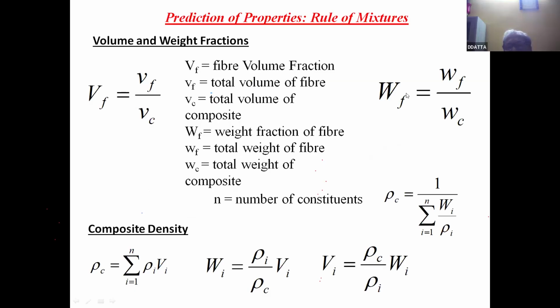These are some of the relationships that we use in the rule of mixtures. This is a very important parameter, the volume fraction of fibers, V_F. This is the ratio of the total volume of fibers to the composite volume, assuming no void is there. And this is the weight fraction. Sometimes weight fractions are also necessary. That is the total weight of the fibers divided by the total weight of the composite.